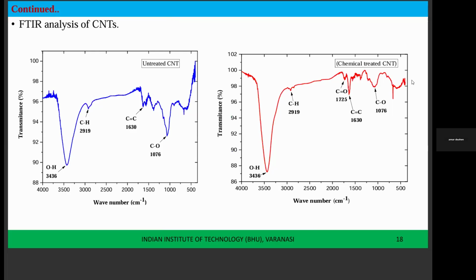So similarly for the CNT particles, multi-wall carbon nanotubes, you can choose a small piece and test it in the FTIR analysis. And you can look once again here, there is a carboxyl group, C double bond O. So you can see it in the chemically treated one. That same one you cannot see in the uncoated one. Okay, so it says that it is functionally treated. There is proper bonding. You can expect enhanced properties. Next slide, please.